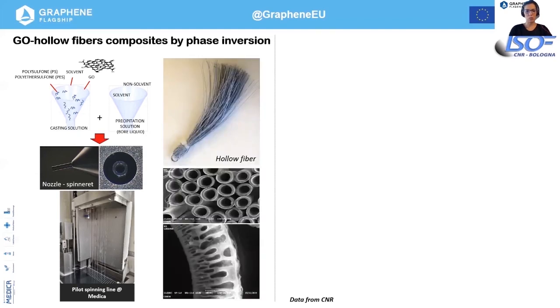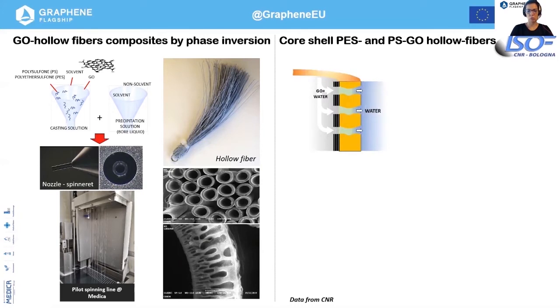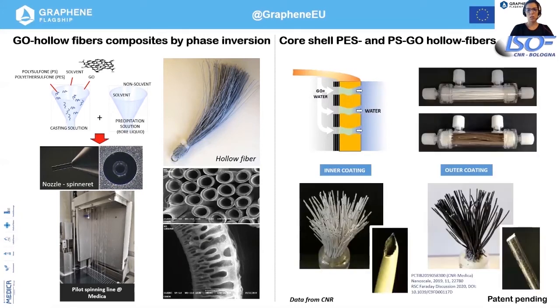These are some pictures of how this hollow fiber looks like. They have graphene oxide inside, and they look gray. The other approach has been developed by CNR, the National Research Council of Italy. It's a core shell approach for creating a coating of polyether sulfone and polysulfone hollow fiber with a graphene oxide solution. This solution is filtered through the hollow fiber, and it is annealed thanks to a fixation step.